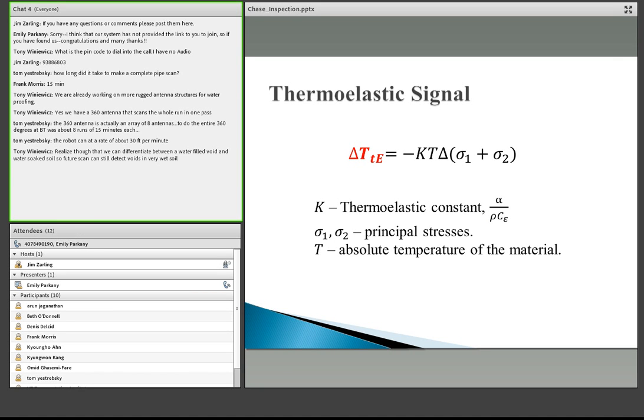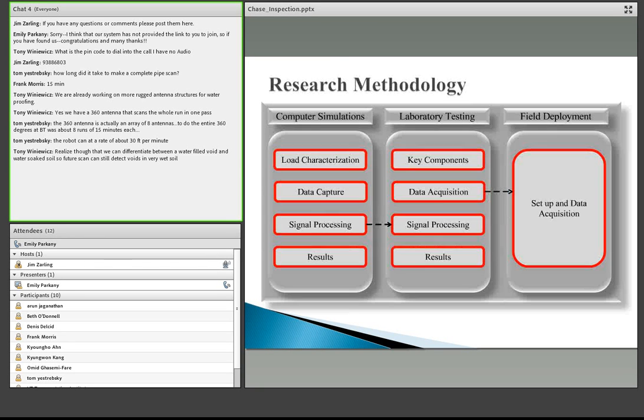The thermoelastic signal, the change in temperature, essentially can be simplified to some thermoelastic constant, which is a function of the material and the ambient temperature, times the change in the principal stresses. So as a detail is loaded, the principal stresses change, and there's a change in temperature that takes place. The magnitude of the change in temperature is quite low. For typical stress changes on bridges, the amount of temperature change is well below 1/100th of a degree. So we have to develop a technology that can be sensitive enough to detect those changes.